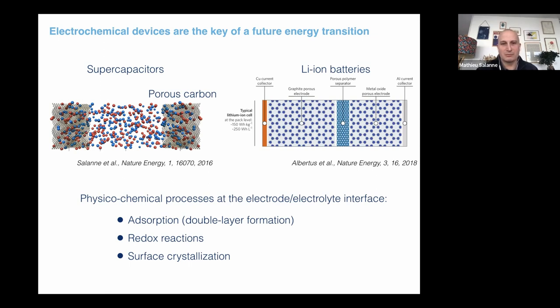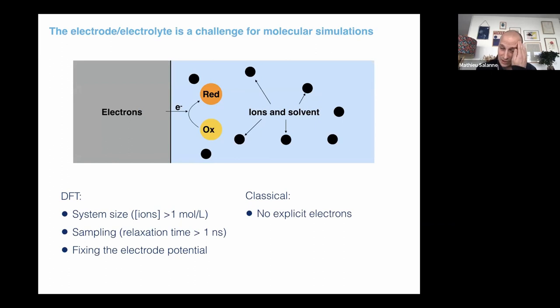So the idea is to be able to simulate most of these events at least, using an efficient method. And of course, the difficulty here is that we are tackling two sides of an interface. On the one hand, we have an electrode, so everything is governed by the electronic structure. On the right, you have an electrolyte, in which of course the electronic structure will play an important role. But in general, you can tackle everything very well using statistical mechanics and classical methods. And so you have to link these two worlds.